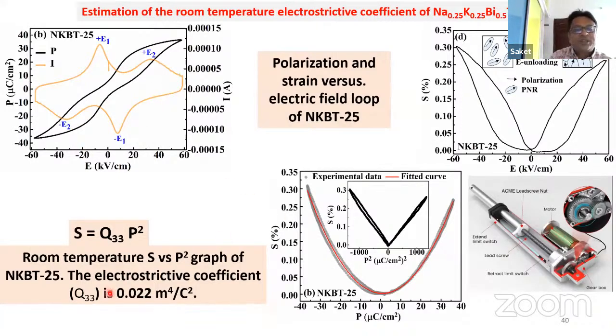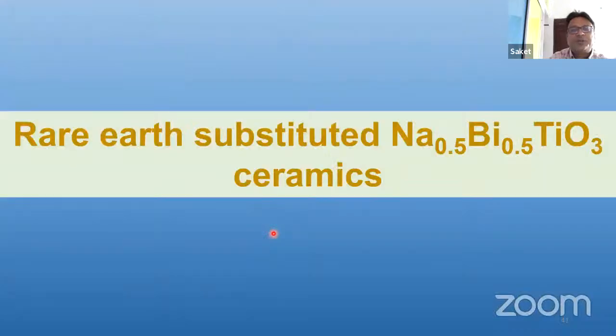Here you can see they have an electrostrictive coefficient also, and they have got 0.022. This coefficient decides how much electric field you need to actuate for the actuator application. Generally for the lead-based system it is around 0.45 or something, but here it is much lower, so you don't need much electric field to actuate this.